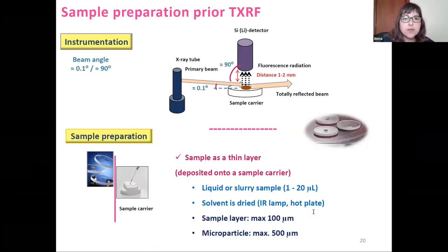In relation with the sample preparation prior to TXRF, it also depends on the configuration of the instrumentation. As we can see, there is a small distance between the sample carrier and the detector. So the sample has to be prepared as a thin film or layer of a thickness of maximum 100 micrometers to avoid damage of the detector and also to have quantitative analysis.